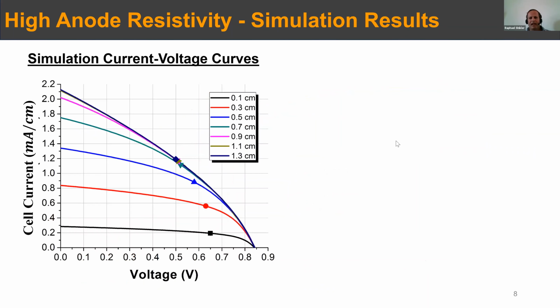You can then go to the maximum power point, try to calculate that, and you can see that as you increase the cell size, at the beginning you have a large increase in the short circuit current, and this starts to saturate as you go to higher and higher current. And also at the maximum power point, which we just track, it also starts to be less efficient to increase it.